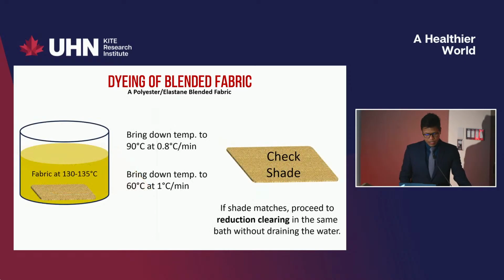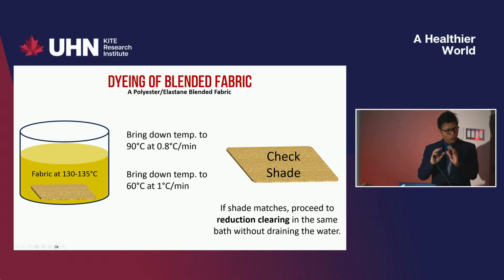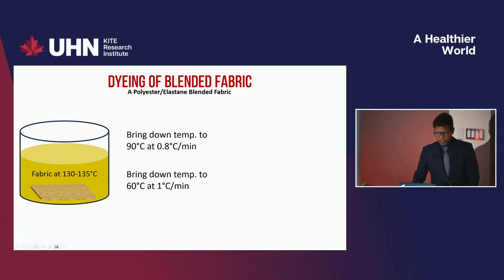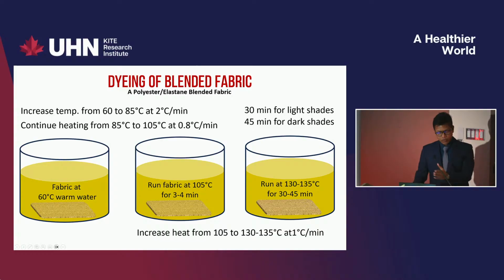Then if I come back again, for instance, with the cooling down temperature, here I cooled at 90 and 60 degrees centigrade. If I don't cool down the fabric at this rate, at this temperature, the polyester will remain open in the polymer scale, and we'll lose a lot of color as soon as they wash the fabric. Also, the final dyeing temperature was around 130, and this is very important. If I go for a 160 degree temperature, I'll be destroying the fiber. The fiber will not remain.